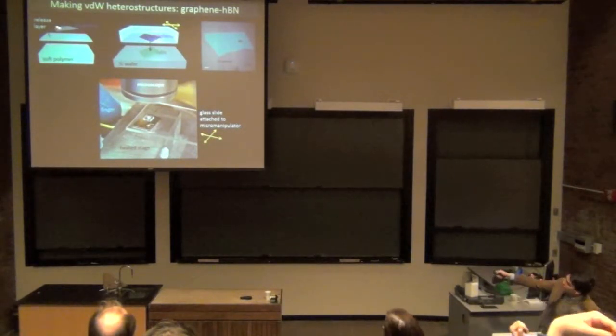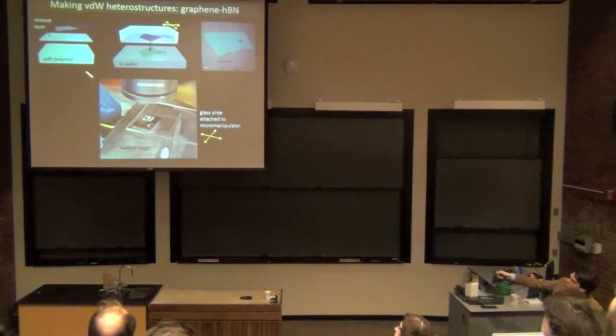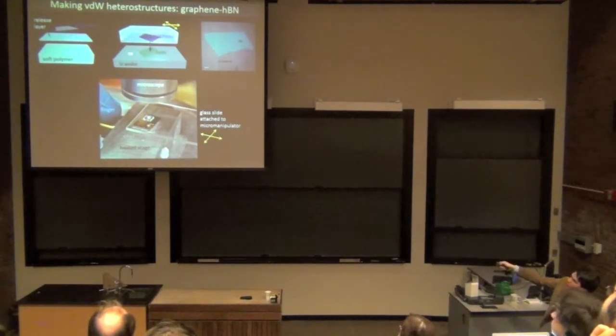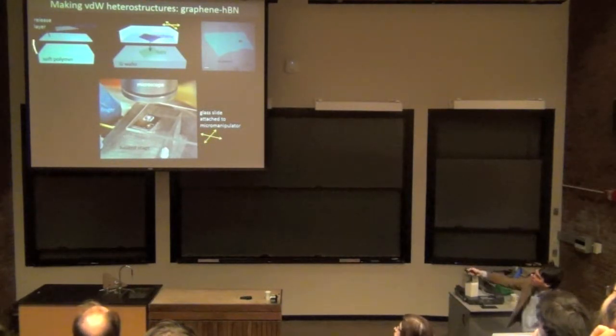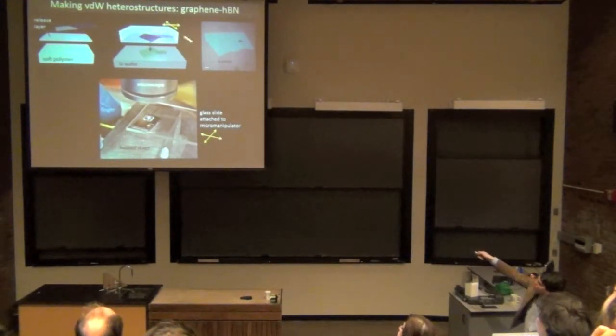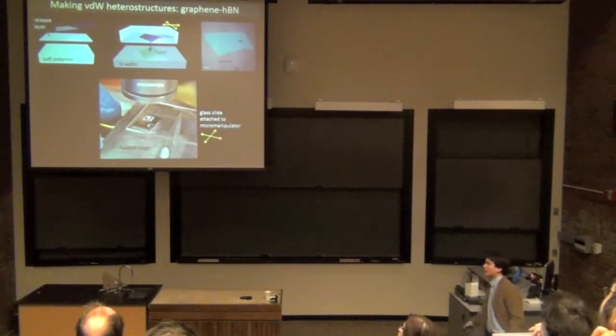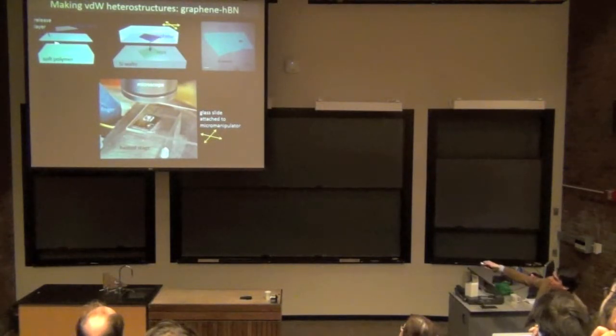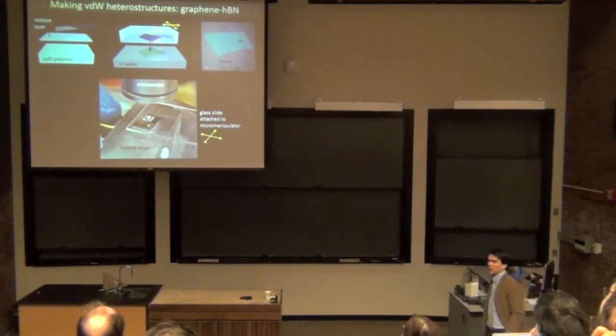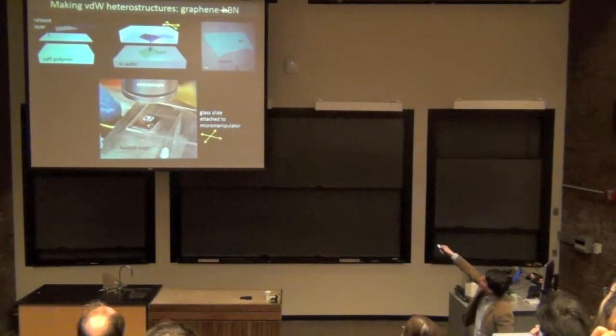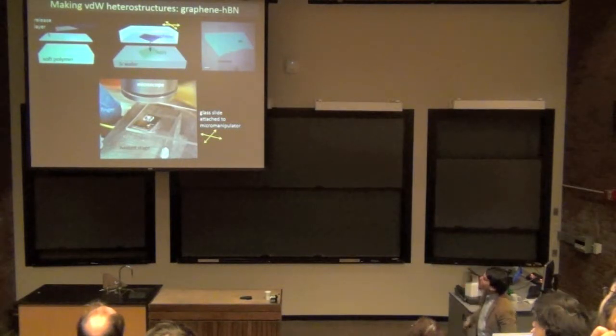And we exfoliate the graphene onto this transparent stack. And separately, we exfoliate hexagonal boron nitride onto a silicon wafer. We flip this thing upside down. We use a micromanipulator to move it back and forth, looking through a microscope, and we press them into contact. And we heat up the substrate, and basically this release layer flows. We throw away the soft layer, and we're basically left with graphene on top of hexagonal boron nitride. And so you get a structure like you see up here in the top right, where you can see the single layer of graphene sitting on top of boron nitride here.